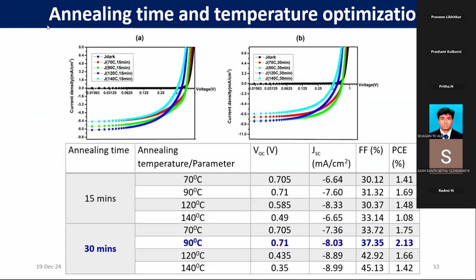We also needed to consider the annealing time and annealing temperature. These are also important parameters in order to obtain higher power conversion efficiency of the solar cells. Like how much time I need to anneal the device, the active layer, and at how much temperature. Temperature also matters, like 70 degrees, 90 degrees, 120 degrees, 140 degrees. We need to play with these many parameters so that we get the higher efficiency device at the end. So 30 minutes and 90 degrees Celsius was giving the highest power conversion efficiency, that is 2.13 percent.